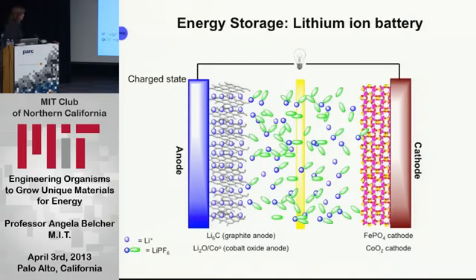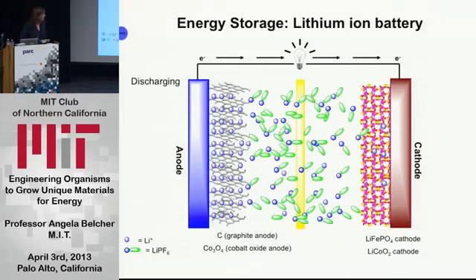And we looked at lithium-ion batteries. And it was a very radical idea at the time, which is we're going to genetically engineer viruses to grow and assemble batteries. And so basically in the lithium-ion batteries, you have an anode and you have a cathode. We looked at making materials for anodes, materials for cathodes, and looked at engineering the electrolyte some for these. And we wanted to do it in a biological way.